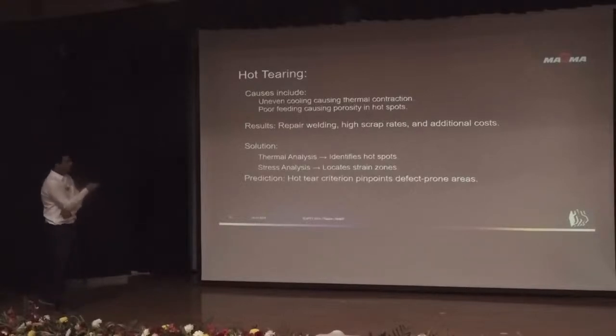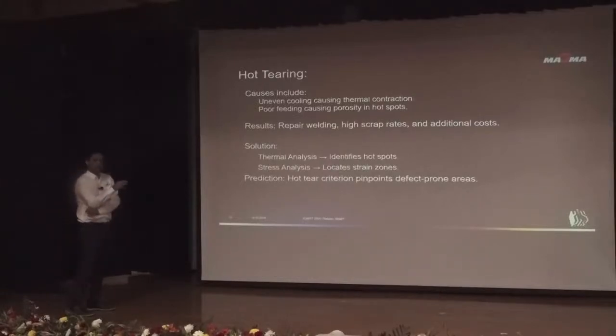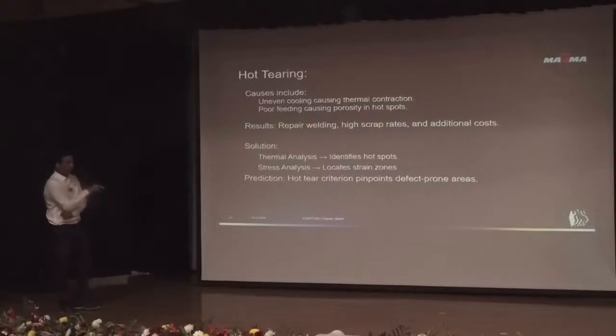There is another thing for stress: we have to minimize hot tear risks in some castings. We use DOE, with variable designs, and do simulations on that. So what are the causes of hot tears? Obviously uneven cooling causing thermal contractions, and poor feeding causing porosity. The results are repair welding and high scrap rates. So what is the solution? Thermal analysis and identification of the hotspots and locations, and stress line analysis, so that wherever strain is developing, we identify those zones.